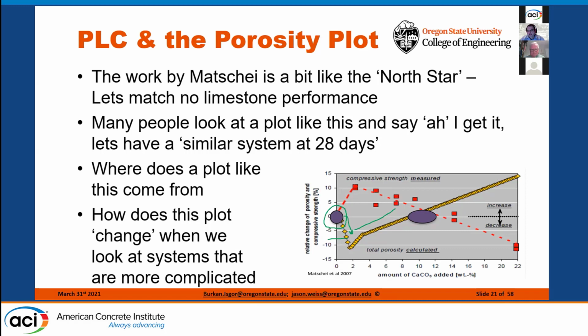As the porosity decreased, again, remember there's a relationship between porosity and strength. The strength went up, and then as the porosity starts to go up again, you'll see the strength coming back down, almost to a point where you're back to where you started in terms of the equivalent strength. And this happens, not surprisingly, at about 10 to 12% Portland limestone.